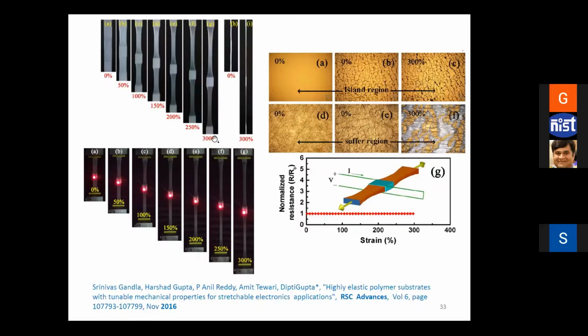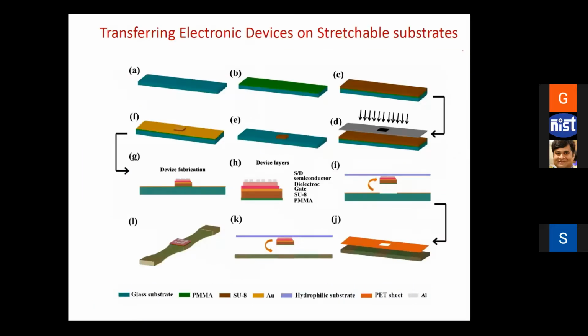We calculated that if you stretch the whole substrate 300%, then in the rigid part only 3 or 4% mechanical strain comes in. Then we put LEDs onto it just to showcase that there is no effect on the glowing of the LED. We also tried to show this by putting gold film on it. You can see over here that at 0% strain, gold film is intact. At 300%, it is slightly breaking, right? This breaking is on the softer part of it. On the rigid part at 300% strain, there is not much breaking between here to here. We also checked its resistivity, which shows that there is no change in the resistivity in the rigid part.